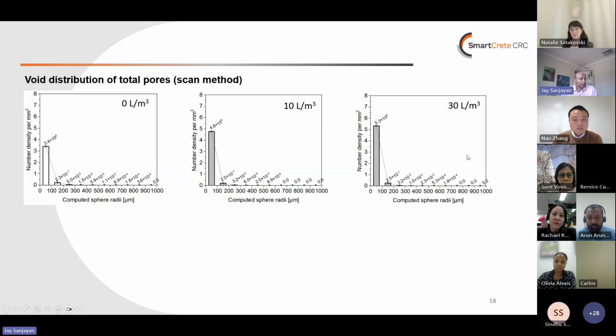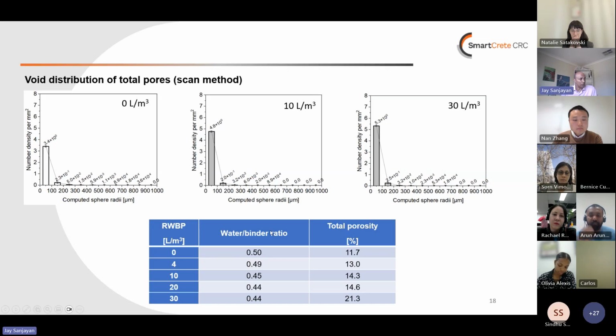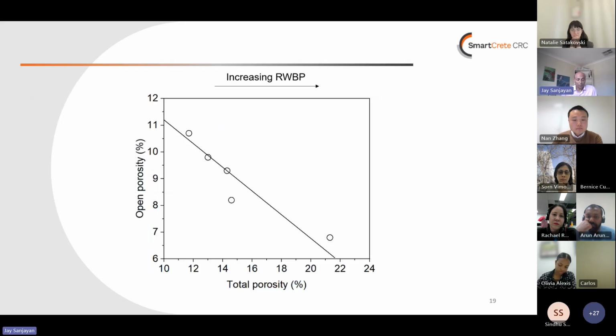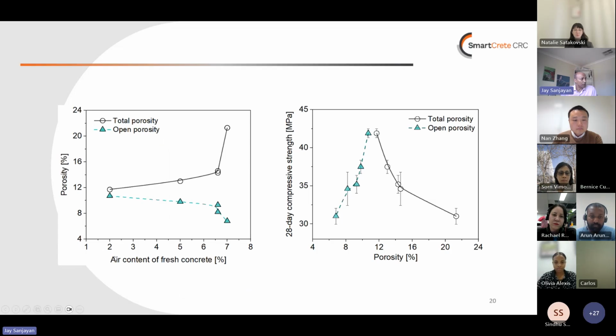And you can see when we increase the paint dose, the large size pores increase. And so you can see the total porosity increases with increasing paint dose. But the most interesting thing that we noted was that the total porosity increases with increasing paint, but the open porosity drops, which is unusual because normally the open porosity and total porosity both increase the same way. But with the paint, we are observing an opposite effect. It's a similar graph here.